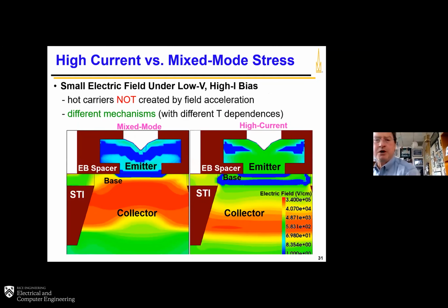High current versus mixed mode. These are two different bias regimes for the transistor on that output plane. And you can see the red is bad. That's very high field, very high impact ionization generation in the CB junction. So you would expect that to have some reliability problems, and it does. But notice on the right-hand side, the high current effect, now the high field region is pushed down into the collector by high current injection effects in the device. But now up near the EB junction, you see the heavy blue region is actually evidence of a different mechanism going on for degradation. And it has a different T dependence.